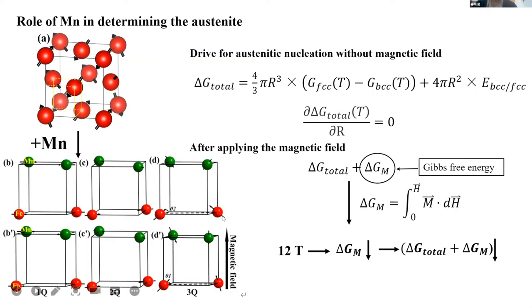Just give the three models to get the thermodynamic result. And finally, we found that with the addition of magnetism into the austenite, the magnetic free energy will decrease significantly.